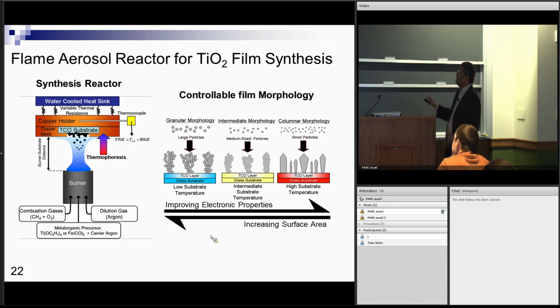So I can then have an intermediate structure, and then eventually this structure sinters out, or as it's growing it sinters out, and I have one-dimensional crystal growth. I have these very elegant looking columnar morphologies which are single crystal and would be very effective in terms of the electronic properties. The surface area is not as high as this. I want a high surface area, as I indicated, to harvest more sunlight, but this might be a good compromise. Okay, so we'll see that.